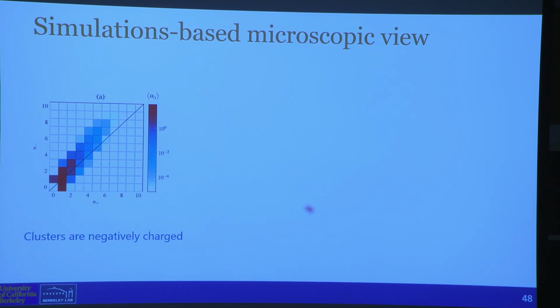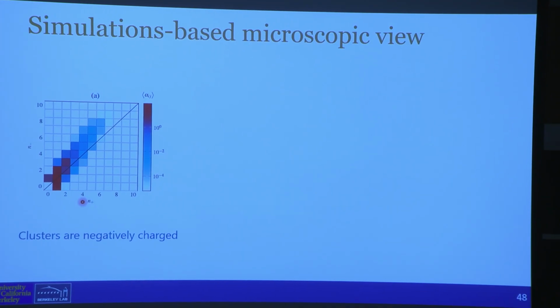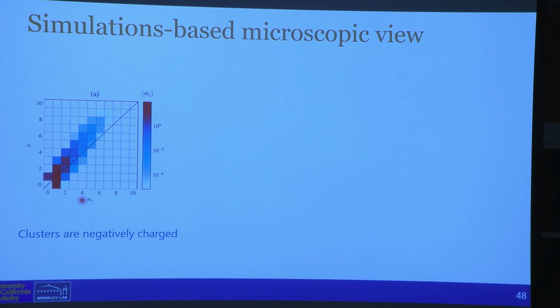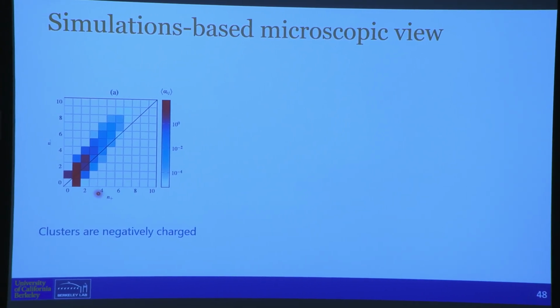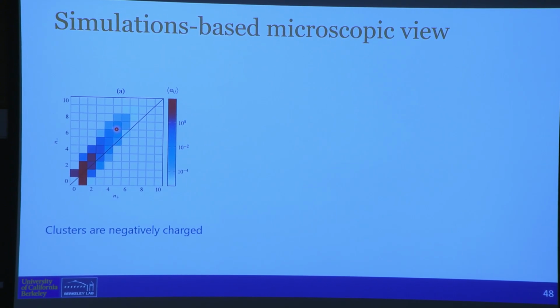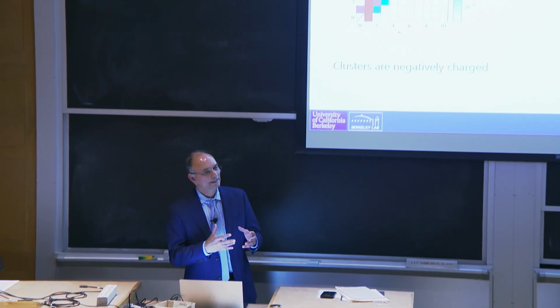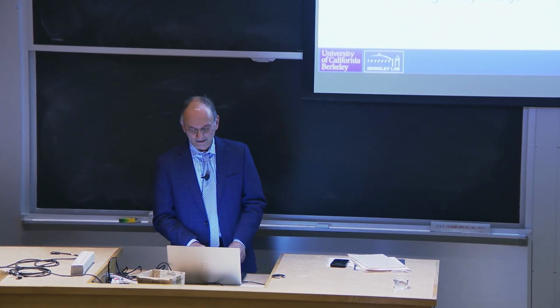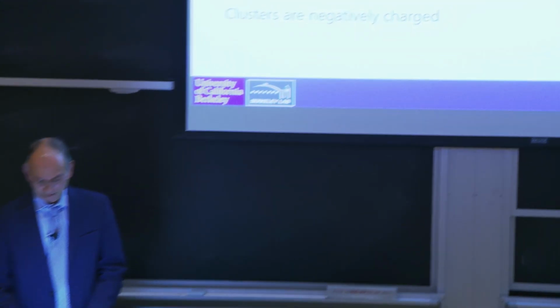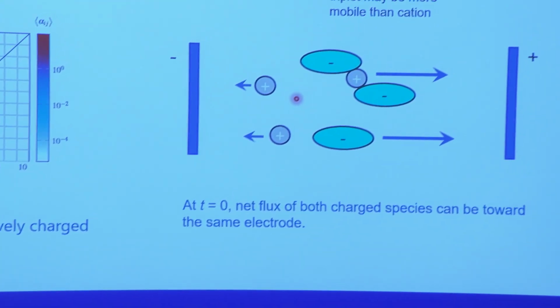In that picture, what they showed, and this is a very useful plot, is the probability of making different kinds of clusters in this PEO. When you have one charge, it's Ohm's law, and you learned this in high school. If you have two charges, you have an infinitum of possibilities. Here they have enumerated some of these clusters, charged, uncharged, and so on. What they said is that most of the clusters tend to drift towards the negative side, and these negative clusters carry the cation with them at a rate that is higher than the free cation. That was their hypothesis for a negative transference number.